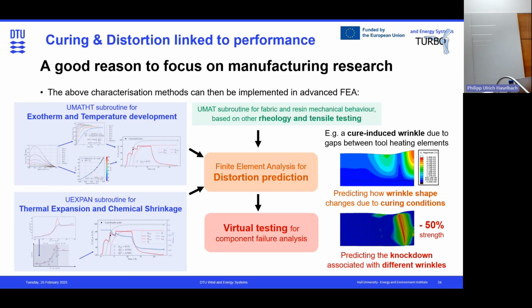This work is quite amazing, I would say, because so far we could often see wrinkles, and I think all of the major OEMs producing wind turbine blades have wrinkles, and so far it was always the goal to try to avoid or reduce those kinds of wrinkles, and this really helps to understand the occurrence of the wrinkles. Before, there was always the thought, okay, what is the origin of the wrinkle? Is that due to the manufacturing, that the labor, because it's quite labor-intensive work, maybe had a small kink in there, and then it starts to originate? And here we could really show that the residual stresses have a big impact.